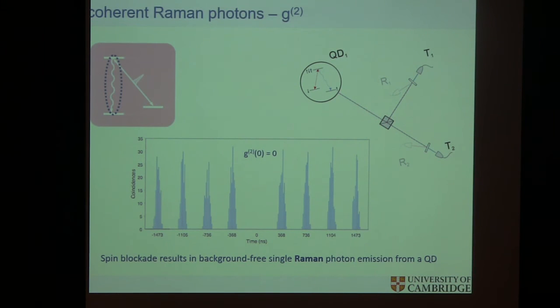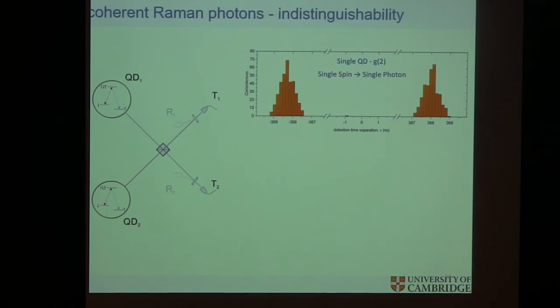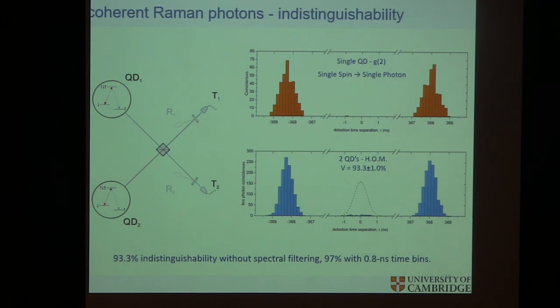And then you actually don't get a photon, simply because there's nothing to emit. Only dark noise, essentially. And then if you do interference of those two, where you postselect the cases where both emit photons, then the interference is now at least acceptable in terms of trying to do these experiments. This is essentially a Hong-Ou-Mandel dip, and the visibility becomes 93%. Again, interfered a long time, no filters, it's just photons as they come.